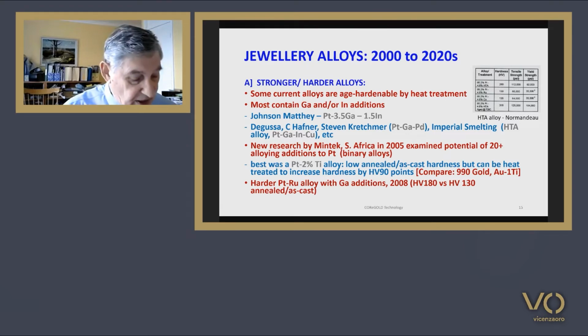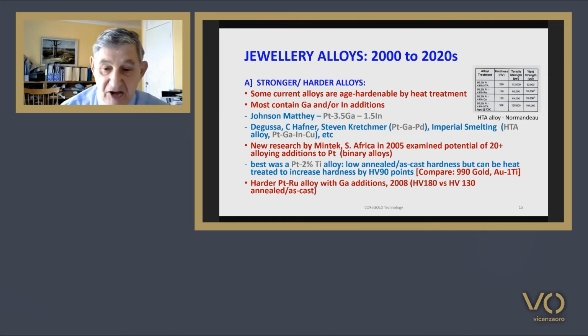More recently, a harder general-purpose alloy, True Plat, has been introduced to the market in the USA by Hoover and Strong. It's a 950 platinum ruthenium gallium alloy that is not age hardenable. It has a high work hardening rate compared to 950 platinum ruthenium, and it has an annealed hardness of 180 Vickers compared to 130 Vickers for the ruthenium alloy.